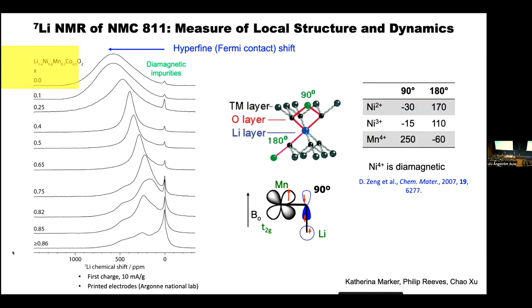And what you can see, even if you don't love NMR as much as I do, is that the spectra change quite dramatically from the fully lithiated to the almost completely delithiated stage. It's very broad at the top, because the lithium sees a whole variety of different local configurations coming from the different paramagnetic ions.